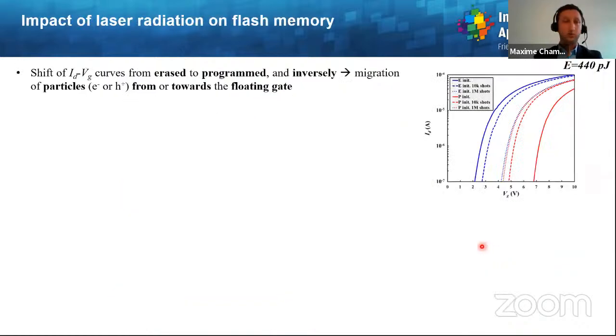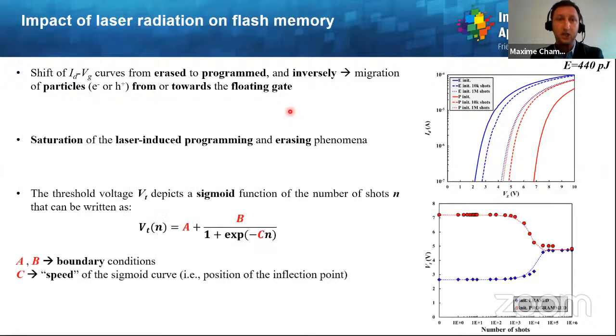So when you perform laser irradiation of the flash memory, here are the results. You start here in solid blue and red lines, either erased or programmed. And you can see that there is clearly an effect of the laser radiation after 10,000 shots and 1 million shots, which means that there is a migration of particles, either electrons or holes, from or towards the floating gate. Then when you repeat this for different numbers of shots, here I represent the threshold voltage as a function of the number of shots, and you can see that the laser-induced programming and erasing phenomena are saturated somehow, here around 5 volts.